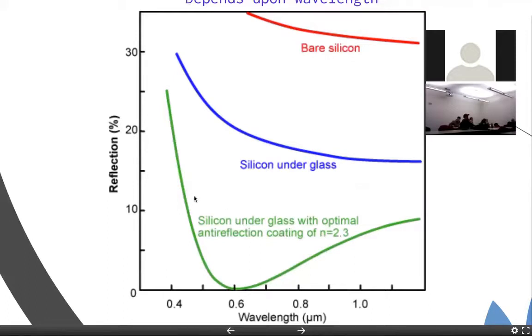Of course, if you are very careful and design a nice anti-reflection coating, as we just did in the last slide, you can get this curve where the reflection is zero at one particular wavelength. So if you only use one layer, you can get it to be zero at one wavelength. This is silicon under glass with an optimal anti-reflection coating with an N of 2.3, that's the refractive index, at 0.6. Of course, at other wavelengths you get non-zero reflection, and that gives you the challenge of how to minimize reflection across a broad wavelength range. For a single wavelength it's possible, but across a broad range it becomes challenging. We'll talk about that also briefly.